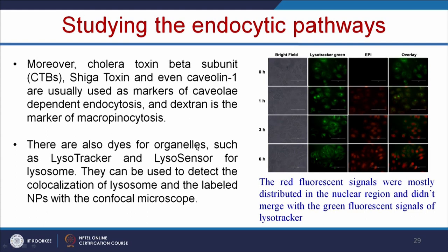And there are several dyes available for specific organelles in the cell. For example, LysoTracker and LysoSensor for lysosome. Okay. So this LysoTracker dye will stain only the lysosome, and they can be used to detect the co-localization of lysosome and the labeled nanoparticles with confocal microscopy. So let us see in this picture, we have used these cancer cell lines, and it is stained with the LysoTracker green. Okay. So this LysoTracker green will stain only the lysosome of the cells, and this is epirubicin. Epirubicin is an anti-cancer drug, which has the intrinsic red color fluorescence. And when we overlay these images, you can see here this anti-cancer drug is entering the nucleus, and your lysosomes, that is the LysoTracker green, are in the cytoplasm. Okay. And here all the red fluorescent signals were mostly distributed in the nuclear region and did not merge with the green fluorescent signals of the LysoTracker. So it shows that this nanoparticle is escaping from the lysosome,